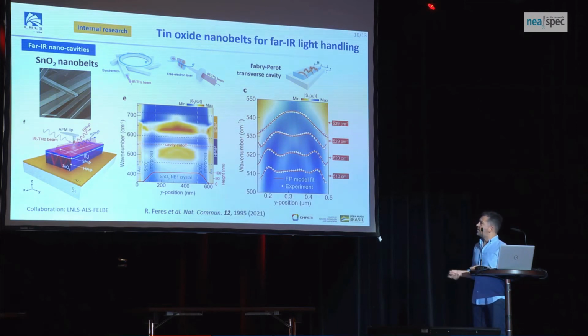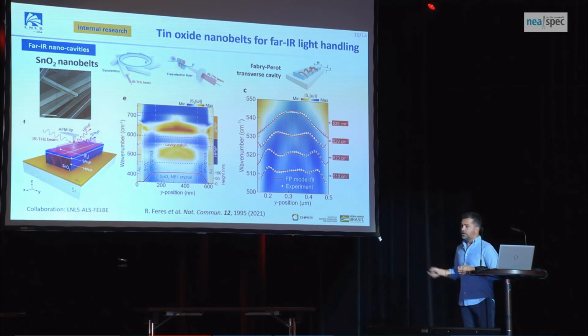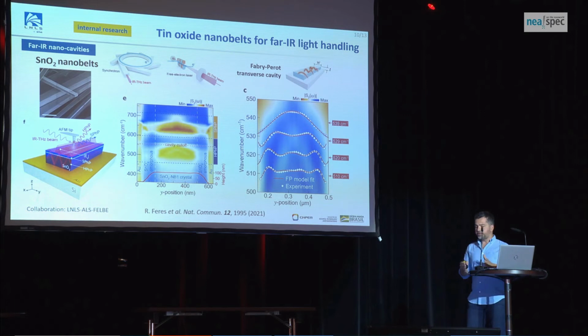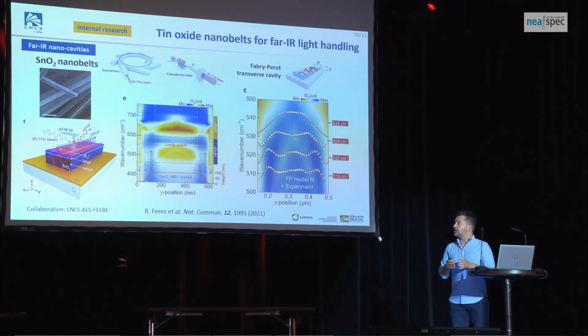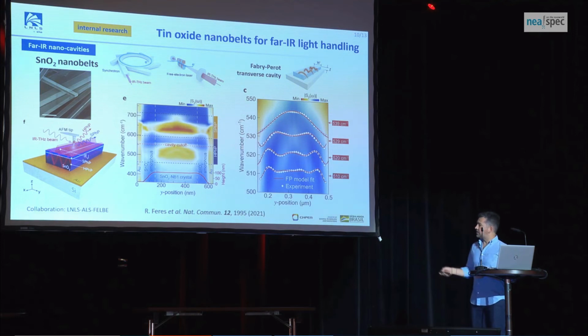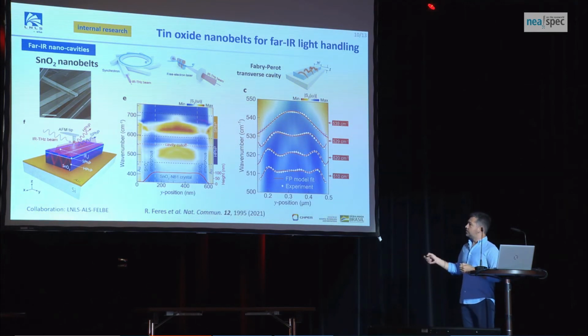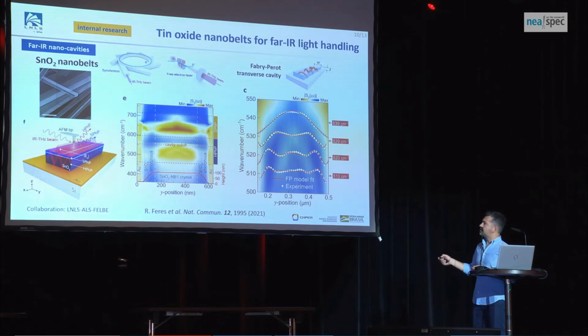The very nice thing here is that this material has some surface phonon polaritons and also volume phonon polaritons. We were trying to see if this sort of sample preparation is any good, for example, for waveguiding of these waves. So we used the synchrotron, we went to ALS to do point spectroscopy and also to take some line scans.